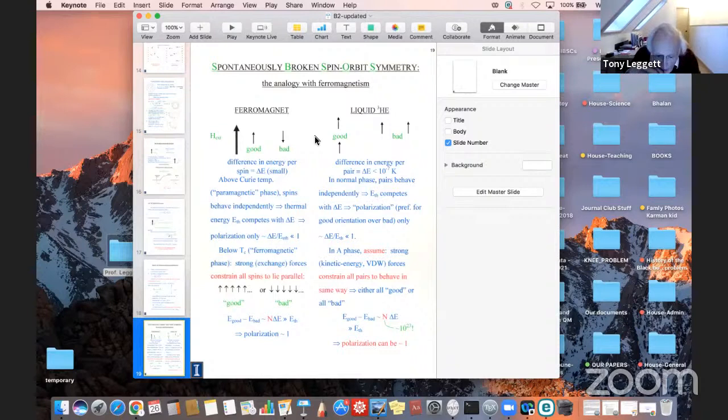Interesting question. There really is no direct analog of that in helium-3, because in an ordinary superconductor, the main reason why the nuclear spins are relaxing is because of interaction with the electrons. And that's why the Hebel-Slichter peak is a very important clue as to what is going on in the electron system, although it's the nuclear spins which are doing the relaxing.